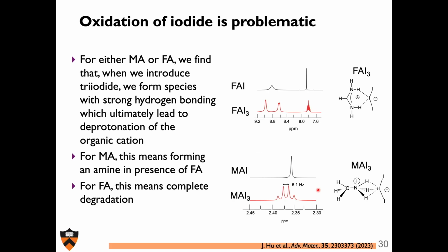So here's what happens. If I have FAI and I put a little bit of iodine in the solution, I will make FA triiodide. And that induces the formation of this type of species here, which basically forms a six-membered ring encompassing the formamidinium cation and triiodide. In both cases, they're very strongly hydrogen bonded. And unfortunately, so strongly that with time, this leads to the breaking of this complex into the constituent components that I showed you, this ultimate deprotonation.